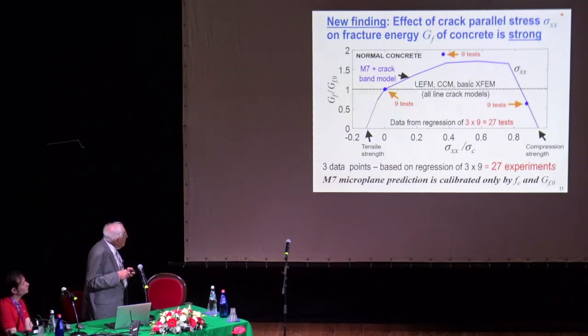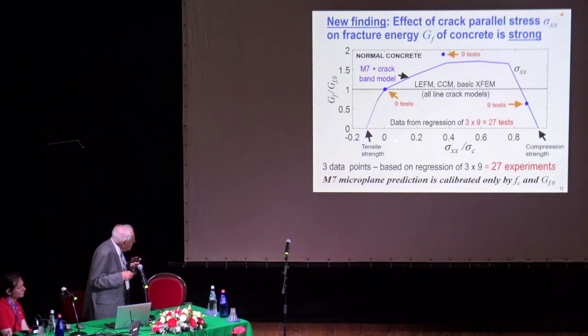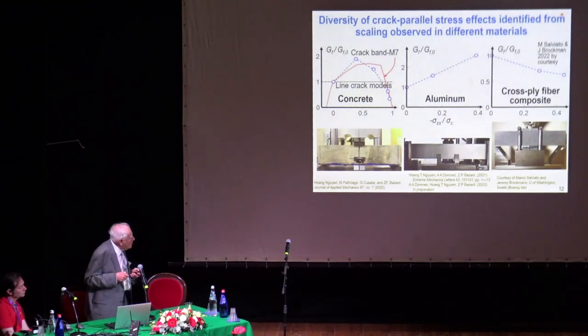For example, for concrete, we plot the normalized fracture energy, so it starts with 1. This is the nominal strength, the crack-parallel stress, parallel to the crack in compression, and it goes from 0, the basic case, up to 1. This is compression failure. We get this diagram. These are 9 tests, so this is a very consistent result. And this is our model, the Bažant microplane model M7, which does not work too well here, but it is perfect here. It's sort of okay. But please note, linear elastic fracture mechanics, the cohesive crack model, XFEM, all these line crack models give nothing, no effect. This is a major effect, and it is significantly path dependent, so it cannot be reduced to a parameter change of G_F, it must be solved incrementally.